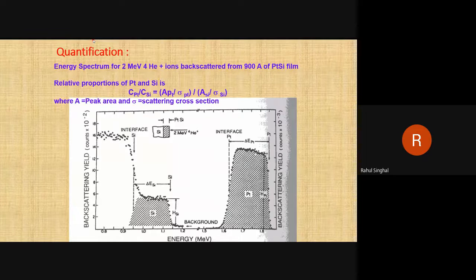Yeah. Interdiffusion is another option. It is basically called mixing. Suppose on the interface here, this sample is deposited on silicon. Silicon is the substrate, and in the shaded area you have platinum as well as silicon. It might be possible that it is not a very clean interface. Some platinum may diffuse into silicon also. If some platinum is diffused into the silicon, it is basically called mixing. If mixing is there, then the slope of this peak from the interface will vary. In that case you will not get the exact position. You see here the slope of the platinum peak is not exactly sharp, it is varying from this angle and from this area also. So just by seeing whether this slope is varying or not, you can get information about the mixing.